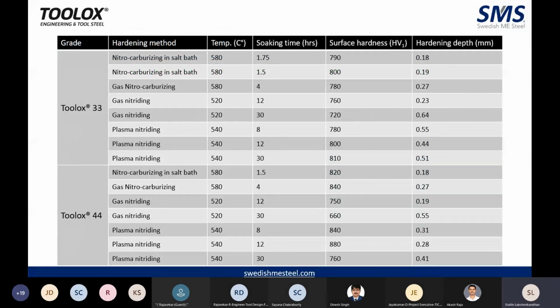So this is a graph which we have done for nitriding of both the Toolox 44 and Toolox 33 grades. Depending upon the surface hardness and the hardening depth that you require, you can choose the soaking time and the temperature. Depending upon your usage and application, you can decide what exactly you want out of the material. So this guide would be very beneficial for you when you do nitriding.